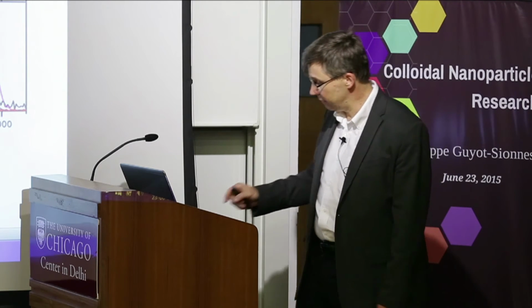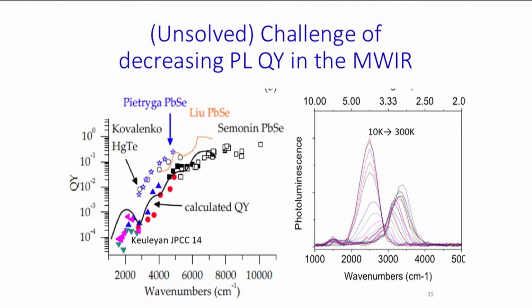Of course, it's totally deceiving. If we actually look at how the efficiency varies with wavelength, we see this systematic drop by 4 orders of magnitude as we go to longer and longer wavelengths. And so this is actually a challenge that we face at the moment. We do not know how to improve this.